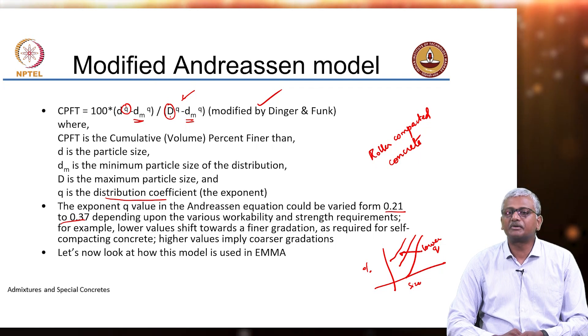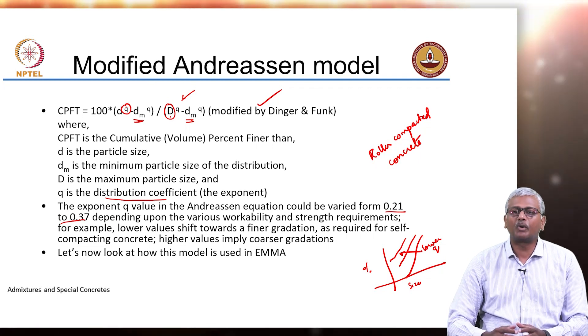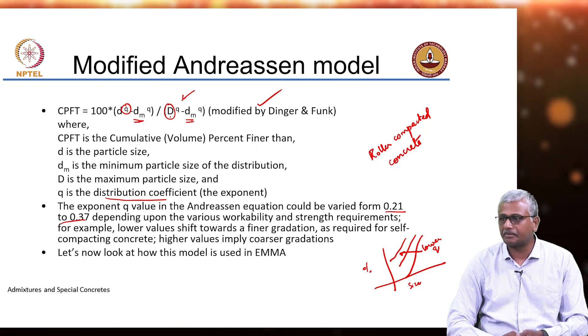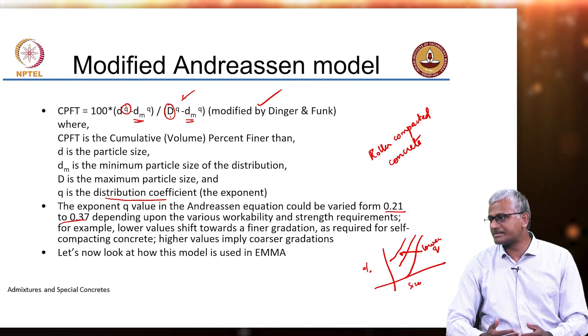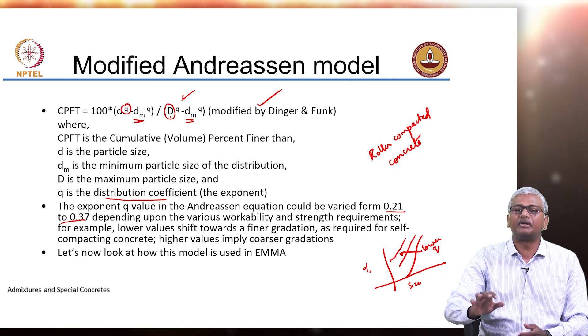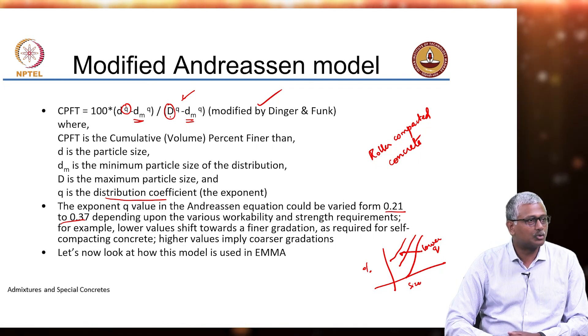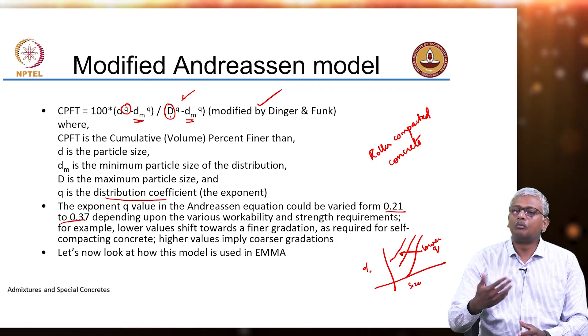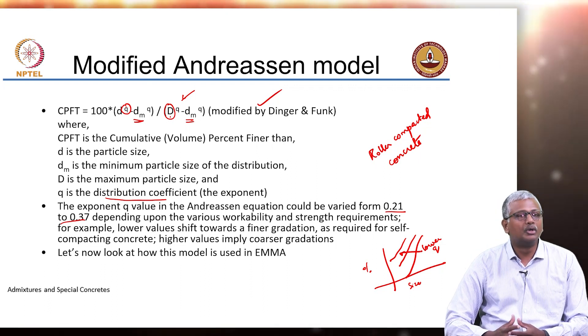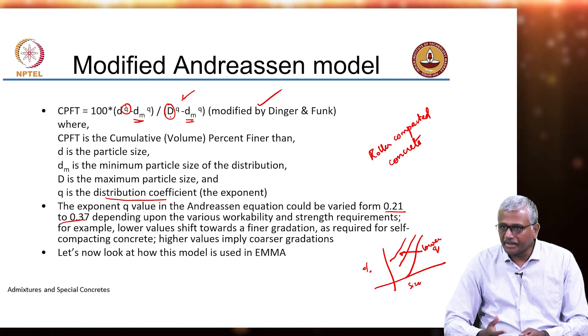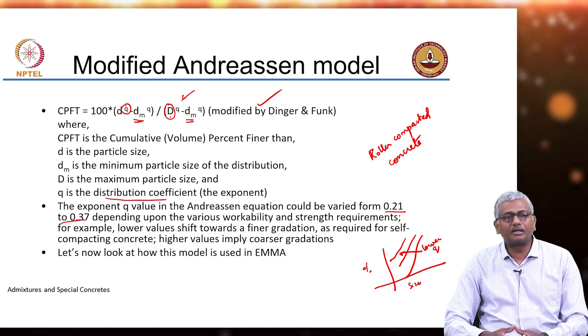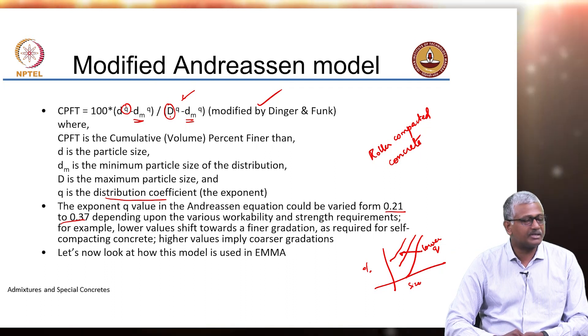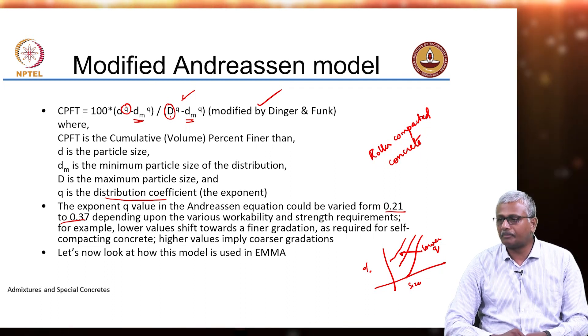If you are considering a mixture of all the aggregates, we provide minimum paste that fills up the spaces left behind by the packed aggregates, and whatever excess space is there provides the workability that carries the concrete during compaction. Modern systems tend to utilize particle packing models that are more sophisticated compared to the maximum density gradations that were employed in the past.